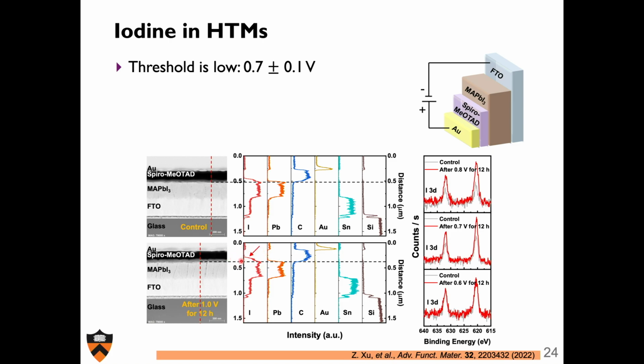And so iodine that gets oxidized will readily enter and dope, and you make a very p-doped spiro at this interface. As such, it makes a really nice ohmic contact. So it's a great ohmic contact. But it also has other drawbacks, because I now have this possible bath and source of triiodide, which is dangerous.